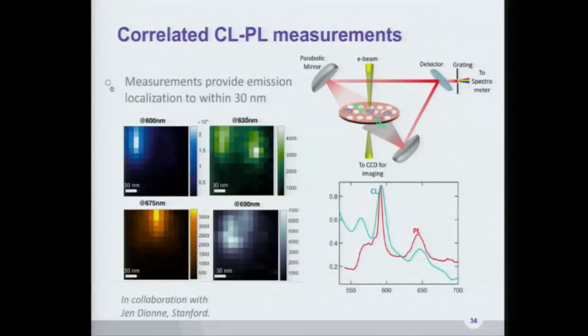So what we said is, how about we start thinking about correlating what is measured for hBN. Identifying which defect it is has been very challenging. I won't try and review all of that work in the next couple of minutes I have, but we said maybe there is some way that you could correlate the optical, morphological, and some electron beam property of the material. And with those three things plus theory combined, you would know everything you wanted to know about this material. This is in collaboration with Jen Dionne at Stanford. They're able to do CL, PL, and TEM, maybe not all at once, but in the same column, on the same sample.